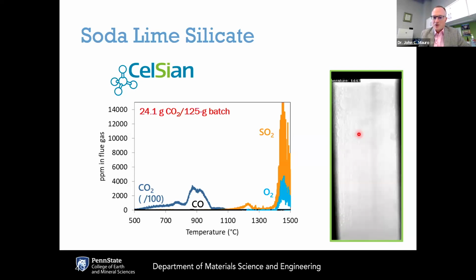We've got SO2 blisters that are being released. They're increasing the size of the bubbles. The viscosity is going down so the bubbles can evolve to the top. And as we get to 1500, everything calms down and you get a nice homogeneous glass here around 1500 degrees C.